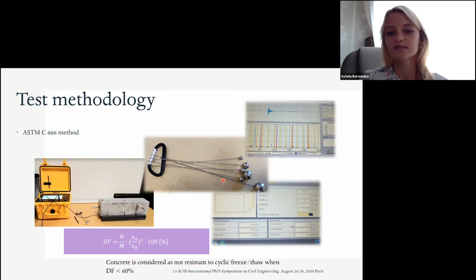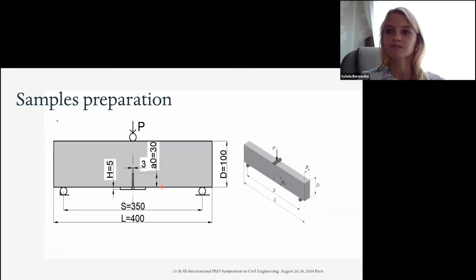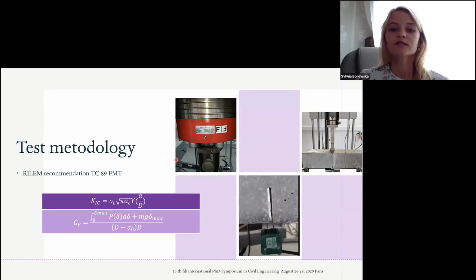Every 50 cycles, the decrease in high-strength concrete frost resistance was controlled by measuring the change in the sample's length and modulus of elasticity. The fracture mechanics parameters were determined on the basis of RILEM recommendation and the methods developed by Jenq and Shah and the 3-point bending test.